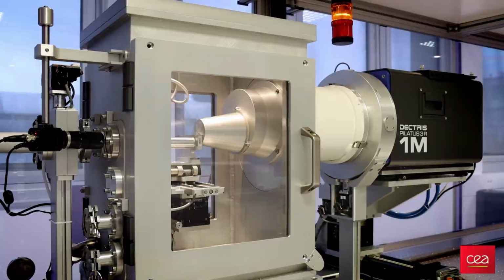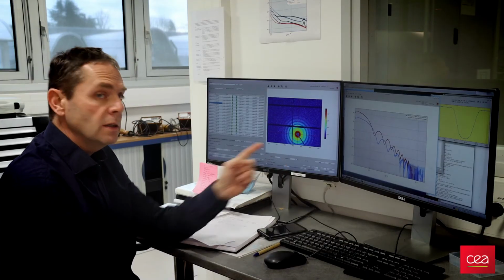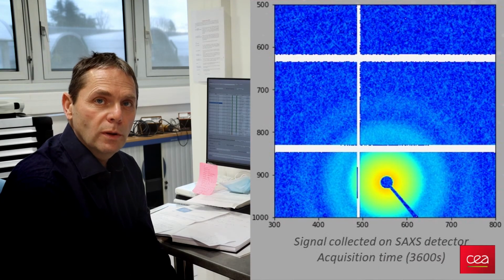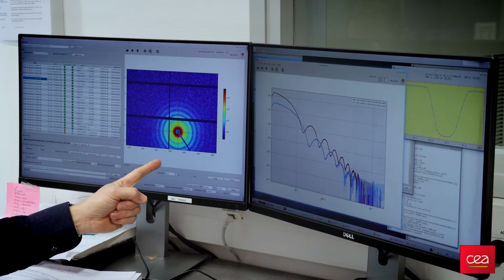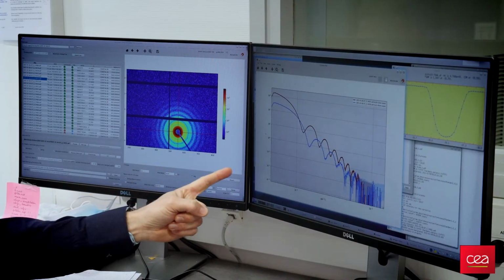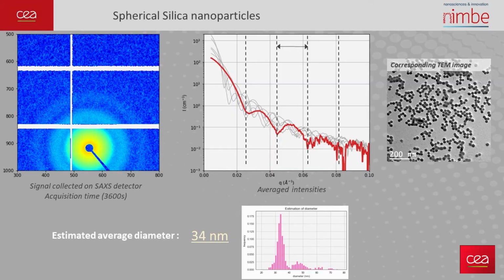From the detector, we obtain an image representing the X-ray scattered by the samples. This image is used to plot the intensity as a function of the scattering angle. The shape of the signal as a function of the scattering angle is sensitive to the nanoparticle size, shape and polydispersity. The intensity of the signal depends on the sample composition and concentration.